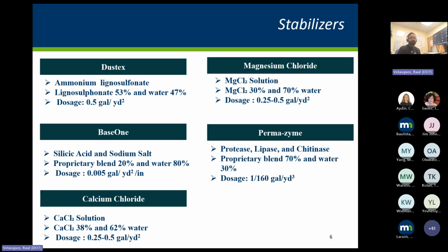In terms of materials, it's funny, this study comes in 5s. They selected 5 stabilizers: 2 non-proprietary standard stabilizers, magnesium chloride and calcium chloride, and 3 proprietary stabilizers. Each stabilizer differs in chemical composition and recommended application dosage. This slide shows the dosage recommended by the manufacturer that was used for building the sites. The different chemical composition of each stabilizer will influence performance, environmental behavior, and effectiveness in road performance. We'll show some high-level results in the next few slides.